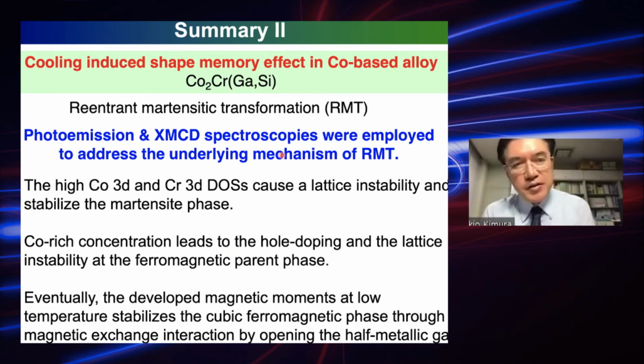So let me summarize my talk. We have studied the cooling-induced shape memory effect in terms of the electronic structure for the Co2CrGaSi system. This shows a reentrant martensitic transformation at low temperature, using photoemission and X-ray magnetic circular dichroism experiments. We have observed a high density of states made of cobalt 3d and chromium 3d orbitals, which may cause a lattice instability and stabilize the martensitic phase. Actually, cobalt-rich concentration leads to hole doping and lattice instability at the ferromagnetic parent phase.